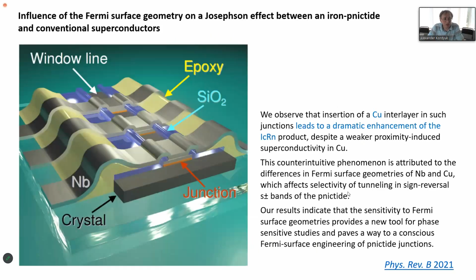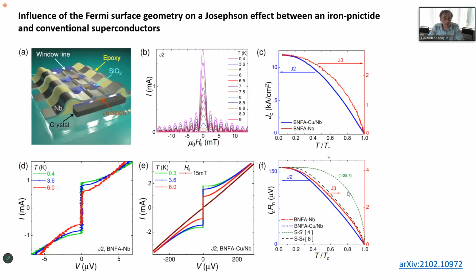It is more technologically difficult, and it is also difficult because for these superconductors you usually have sign change of superconducting parameters. It is of course a special topic, very big, but I want to say that we were the first who managed to realize the Josephson junction between normal niobium superconductor and the new iron-based superconductors, which are known to have a so-called S plus minus superconducting order parameter. That complex superconducting order parameter is changing sign, has different sign on different Fermi surfaces.